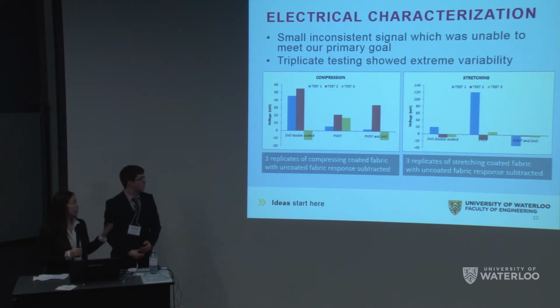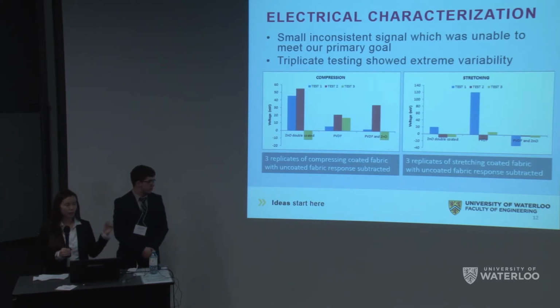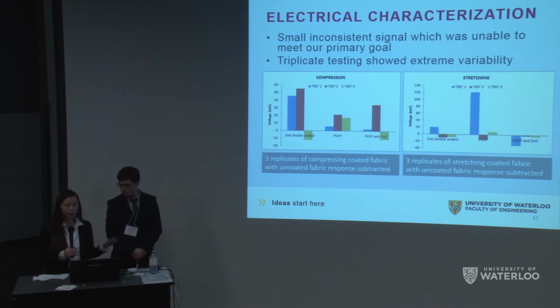And we actually didn't realize at the time that the main reason this was poor was due to the misalignment of the nanowires. And we also thought that maybe it was the ZnO just not displaying a large enough piezoelectric response. So then we compared PVDF polymer to ZnO, because PVDF is a commonly used piezoelectric polymer, which should give us a good reference. So that's why there's PVDF in the charts. And you can see that the PVDF also had really poor response.